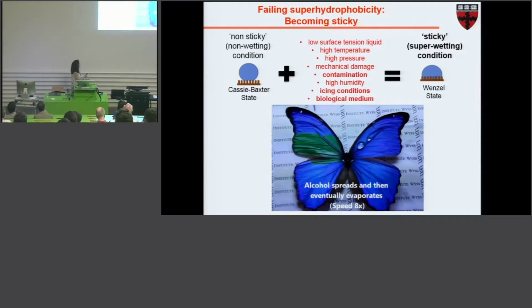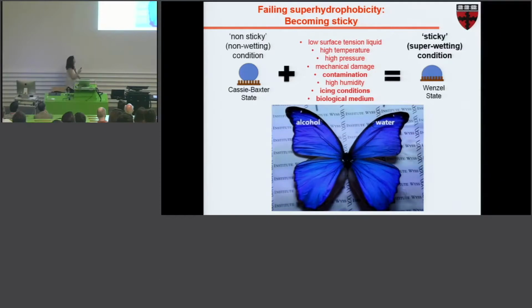So if I use low surface tension liquids, and this movie playing here shows it very well, the wings of butterflies are superhydrophobic, and when water is touching them, it repels it. But when alcohol is touching it, it actually infiltrates the structure. So it cannot handle low surface tension liquids, it cannot handle surfactants, it cannot handle any contamination or mechanical damage or high pressure, and all that would change the property from this non-sticky condition to a highly sticky condition, when the liquid is capable of interacting with the entire surface, not only with the tips of the structures, but also the entire structured interface.